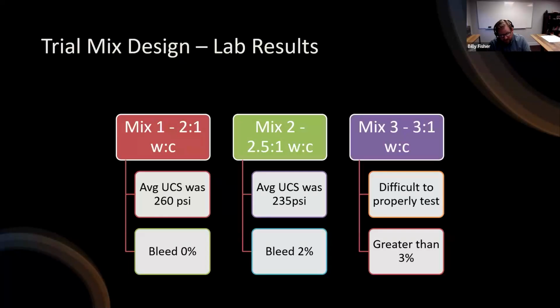Some of the results from the mix design: mix one in the lab, we had confines of about 260 psi and roughly zero bleed. Mix two had similar breaks, but a greater amount of bleed. And then mix three we determined was not really going to be an option because the bleed was greater than 3%, and they also had difficulty removing the samples from the molds. It just was not setting - it was too high of a water cement ratio.